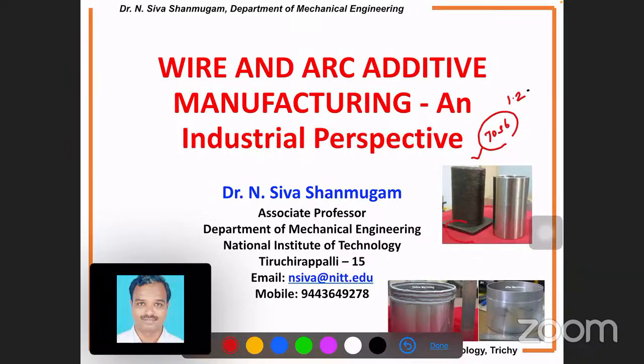We have the substrate at the bottom. After completing the build, if you zoom into my presentation, you can see layers placed one above the other, layer upon layer, to get the desired height. After that, I used a conventional lathe and boring tool to remove the material inside, and a turning tool, a single point cutting tool, to remove the material on the outside surface.